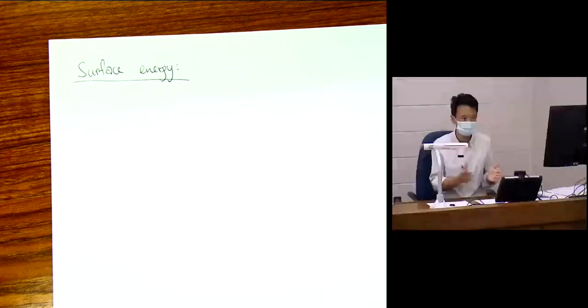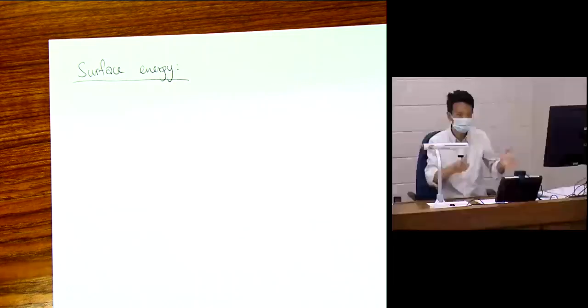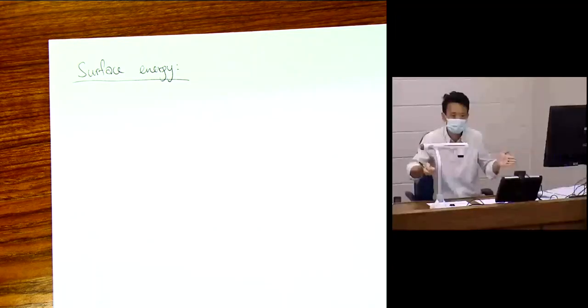It's hard to control. You want to pull out a soap film. You have a kind of frame, you dip some soap, and you start to stretch out a film. If you can stretch it out as large as possible, that's really cool. But then it's very difficult because at some point it breaks. So that is a perfect experiment to measure surface energy.